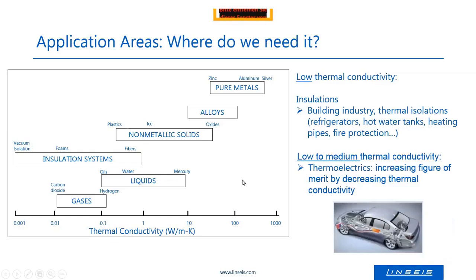Then a special application where you want to have medium thermal conductivities are thermoelectric materials. Thermoelectric materials are materials when you apply a temperature change to them, then they can transfer the heat energy into electrical energy. And the goal is to increase the figure of merit, which is an efficiency factor. And for this, you need low thermal conductivities. But you need also high electrical conductivity for that. And in theory, it's difficult to have high electrical conductivity and low thermal conductivity. So for the most thermoelectrics, we are in the medium or even low range of the thermal conductivity.